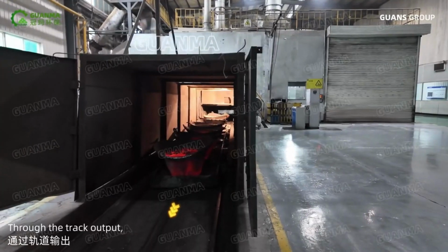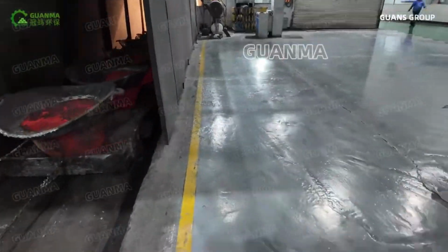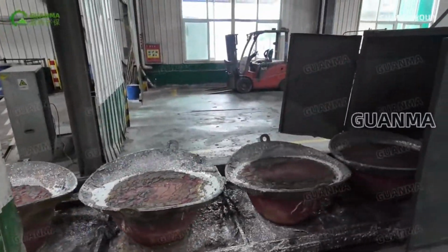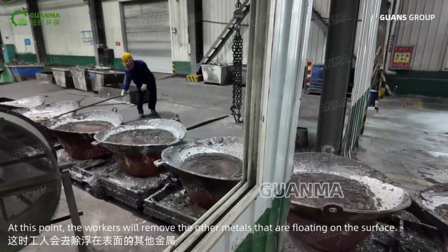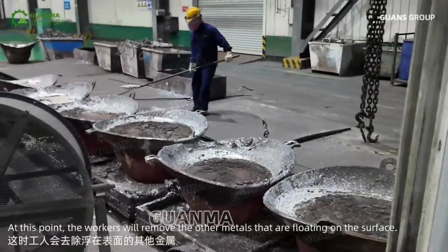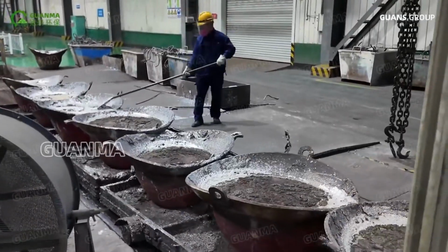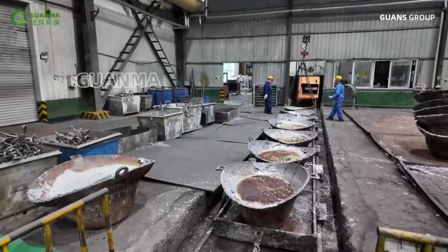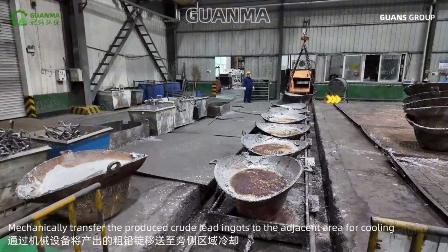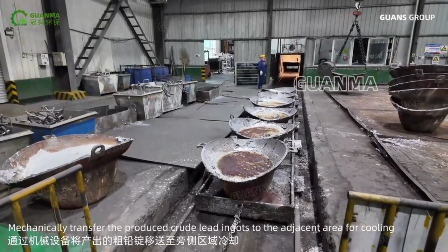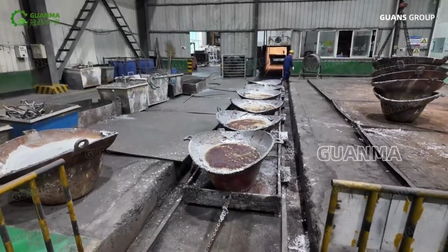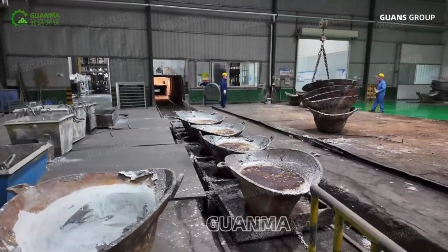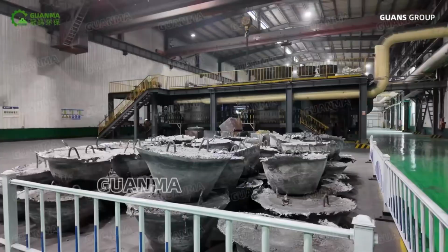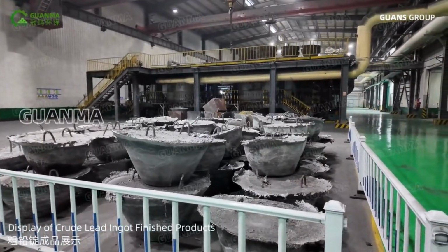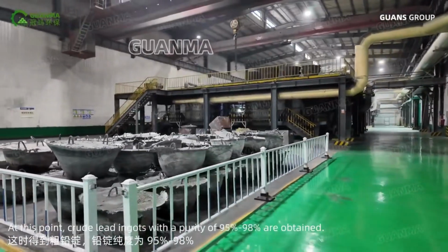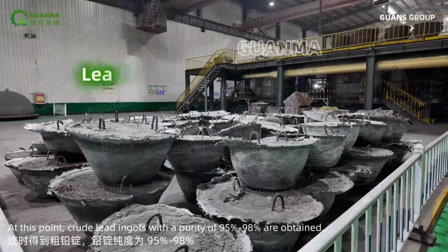Through the track output. At this point, the workers will remove the other metals that are floating on the surface. Mechanically transfer the produced crude lead ingots to the adjacent area for cooling. Display of crude lead ingot finished products. At this point, crude lead ingots with a purity of 95-98% are obtained.